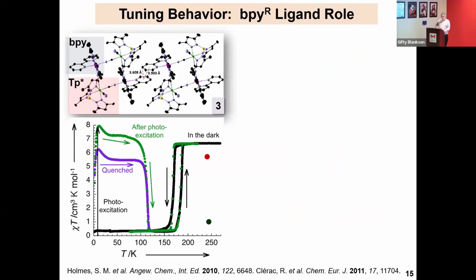All right, magnetic properties. Again, it's red at high temperature, green at low temperature. Lots of unpaired electrons at one temperature, essentially zero at the other. We can access this photochemically. We can quickly cool it. They're not superimposable ever, but again, as we increase the temperature, we follow Arrhenius kinetics. There's some sort of thermally activated state.